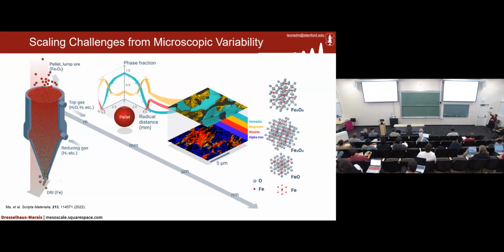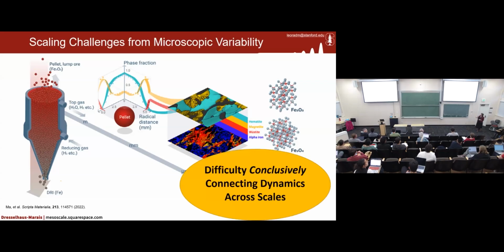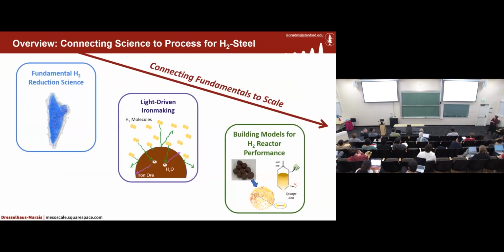The scale of the atoms, when we go from the oxides to the metal, we actually have a 46% reduction in volume. Whereas at the scale of the pellets, actually they swell up as they become more porous. And ultimately, the reactor stops moving, or stops flowing, because all of the pellets get stuck together. So connecting these scales definitively is really the challenge here. So in my group, we work on connecting these scales to understand the most fundamental view of how we could control these reactors.